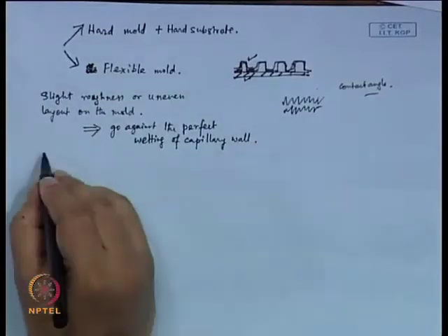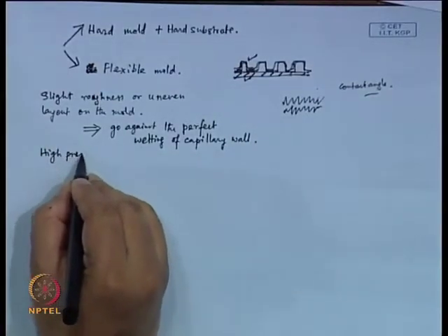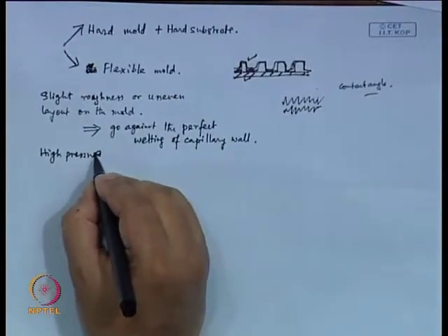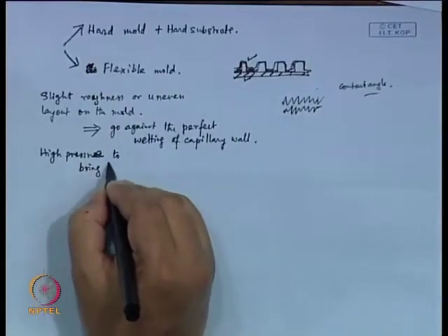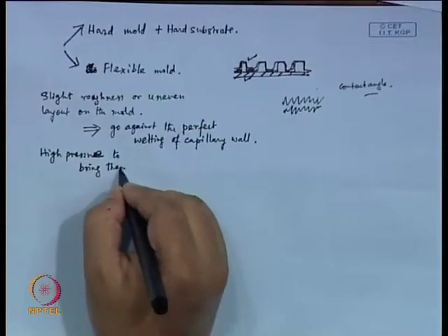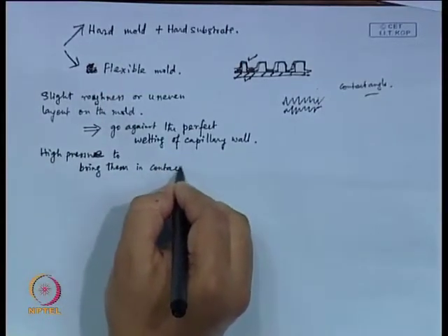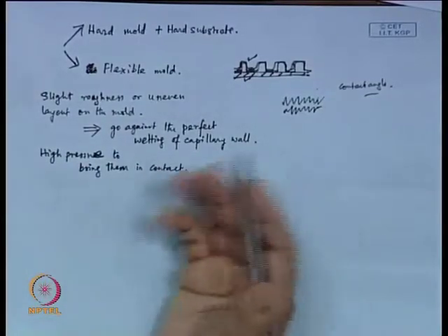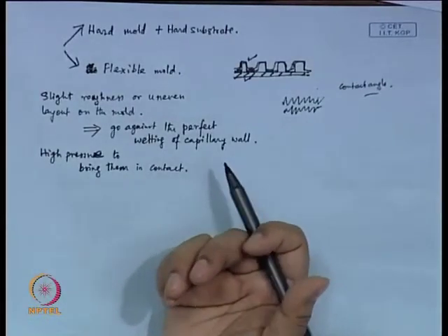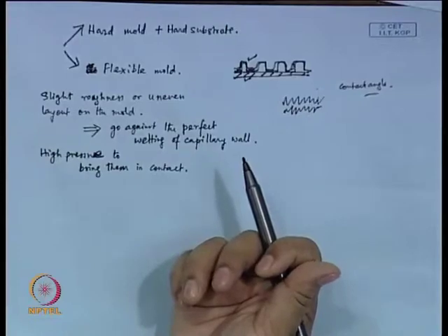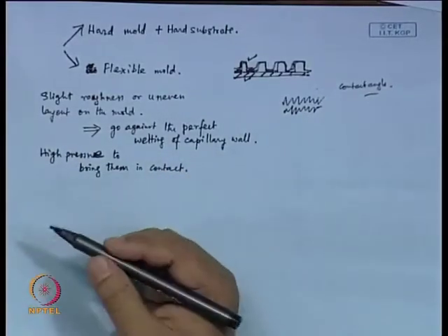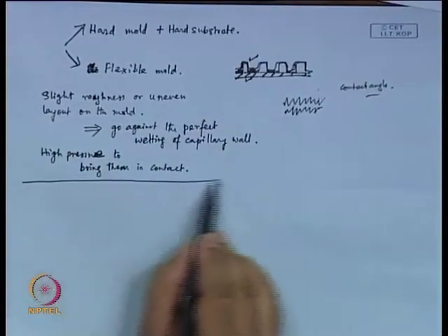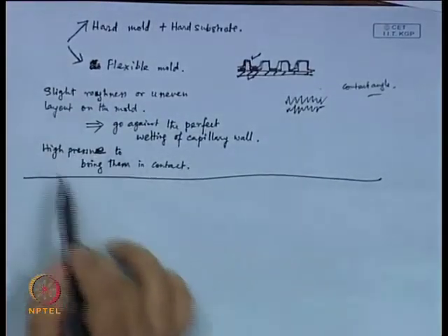So the choice is you need high pressure to bring them in contact, but then probably this capillary filling by capillary action becomes inconsequential, because if you are really employing high pressure, then you may as well use the squeezing to have this material travel. So flexibility in the mold itself has some benefit. Some amount of flexibility should be there to bring this contact.